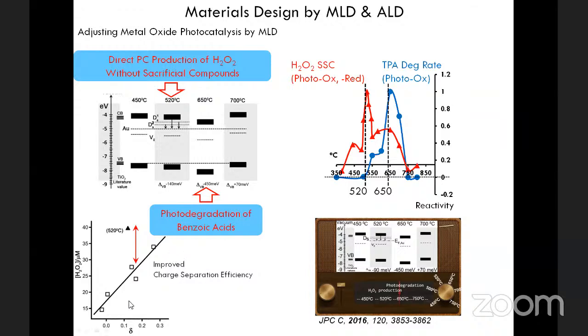And by looking at the deviation from stoichiometry, delta, and the steady state level of hydrogen peroxide, you can see there is a very nice linear fit for all anneal temperatures that are represented here by the different stoichiometry deviations. However, for this 520 degrees Celsius, one can see that the data point exceeds by this much from the correlation, and one can ascribe this enhancement in the activity to the improved electron transfer rate of the photoexcited electrons to the gold Fermi level.